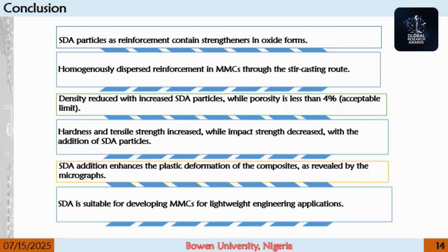Density reduced with increased SDA particles, while porosity is less than 4%, which is the acceptable limit. And also, from the study, hardness and tensile strength increased, while impact strength decreased with the addition of SDA particles. The SDA addition enhances the plastic deformation of the composite as revealed by the micrograph. And lastly, the SDA is suitable for developing MMC for lightweight, engineering applications.